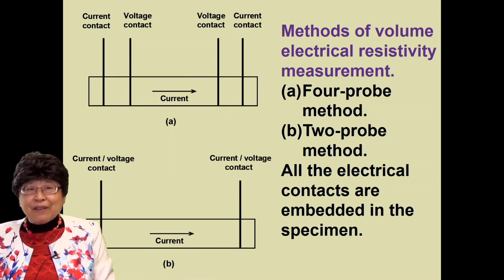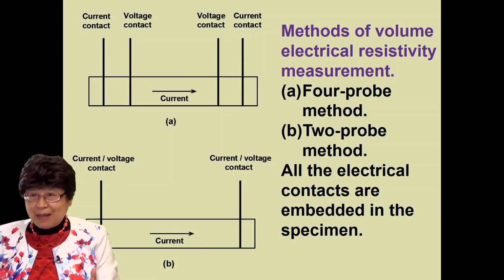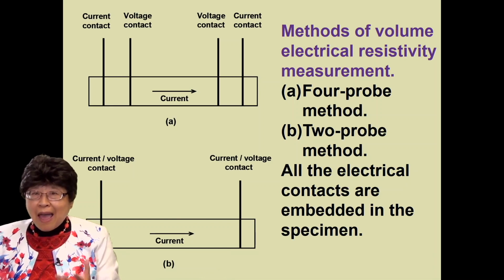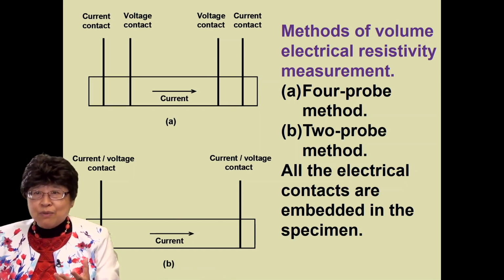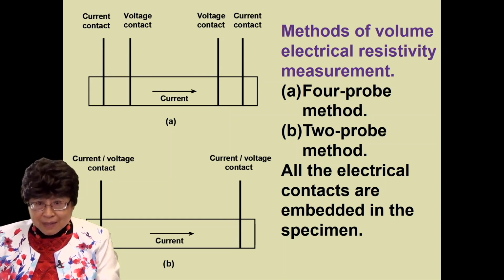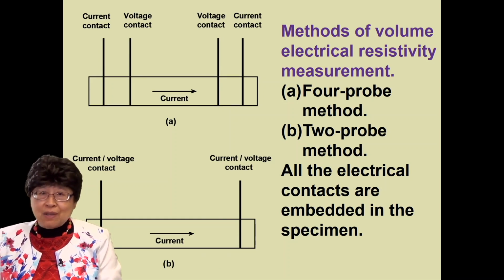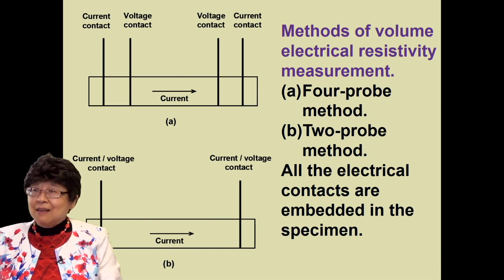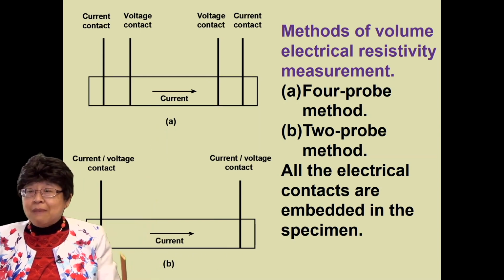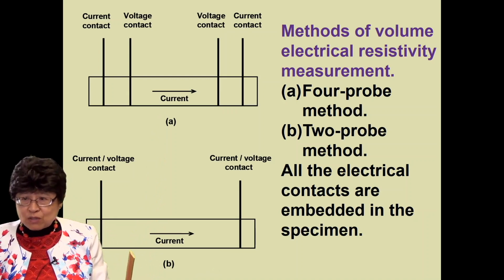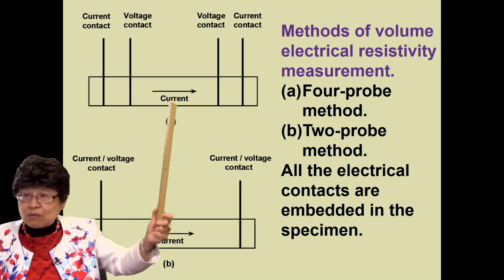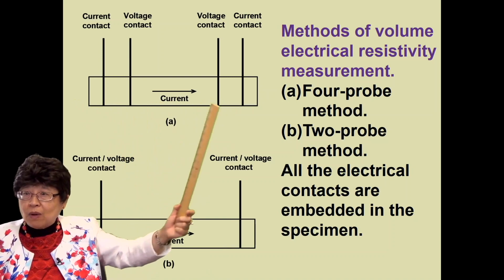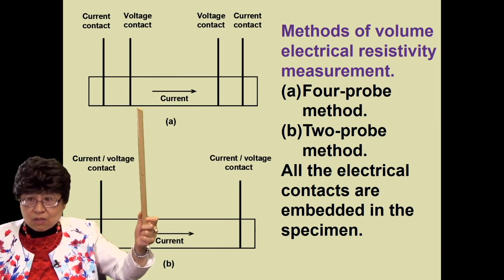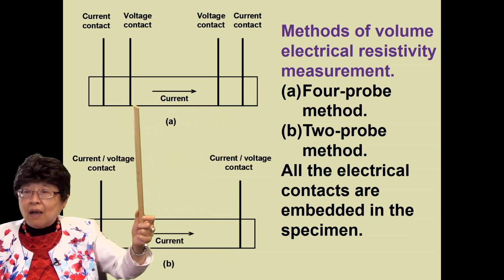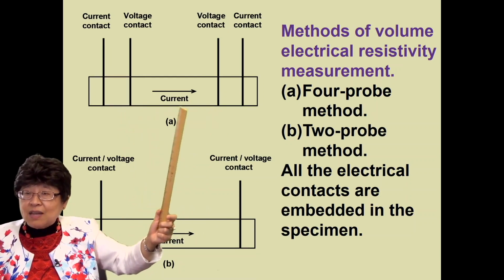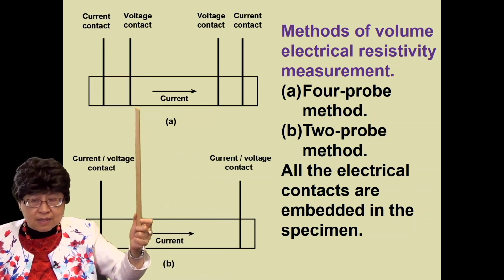Now, having this carbon fiber cement is not enough. You have to be able to measure the electrical resistance change properly. And there are pitfalls of that electrical measurement. There are two methods of electrical resistance measurement. One involves 4 electrical contacts, the outer 2 for current, the inner 2 for voltage. And in so doing, your measured resistance does not include the contact resistance.